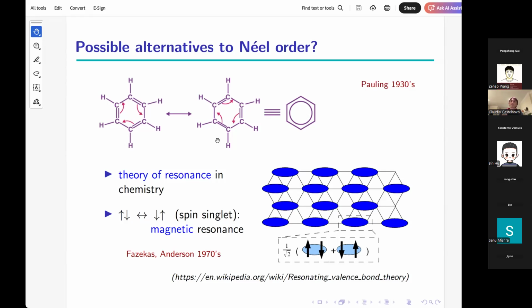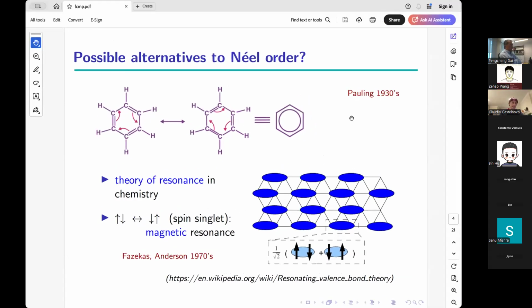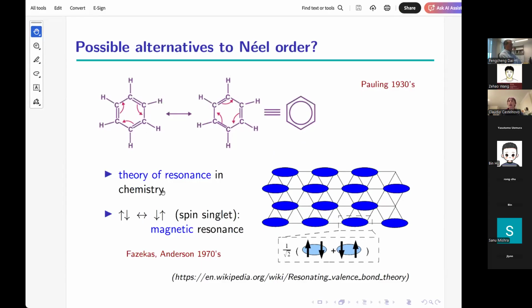But of course, you have 2 possible degenerate ways of doing that. And quantum mechanics, if there is a superposition overlap matrix element between these, will always prefer a coherent superposition of the 2 and lower the energy of the system. And that creates a resonance, typically drawn as a ring on the benzene molecule. The same can happen with antiferromagnetic bonds. If you have an up-down arrangement of spins, that's isoenergetic to a down-up. And if you have a matrix element between these two, quantum mechanics will dictate that the ground state is a superposition, a singlet between the two, down-up plus up-down over root 2.